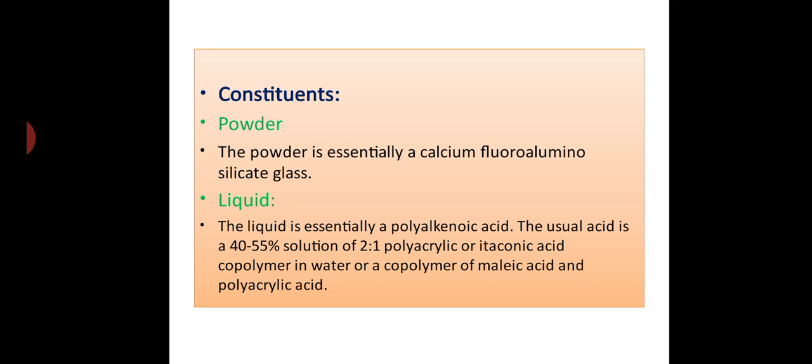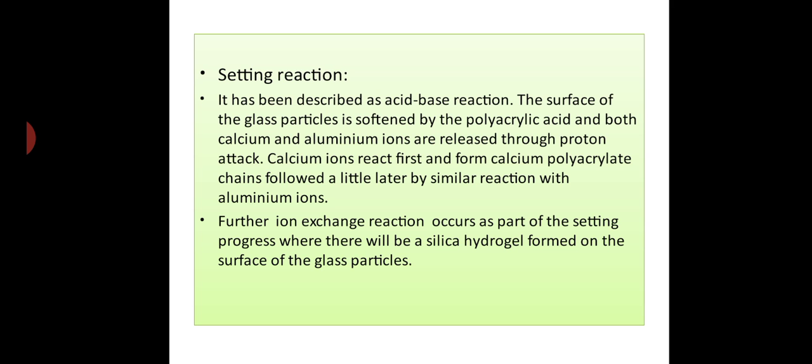The usual acid is a 40 to 55% solution of a 2:1 polyacrylic or itaconic acid copolymer in water, or a copolymer of maleic acid and polyacrylic acid. Setting reaction: it has been described as an acid-base reaction.